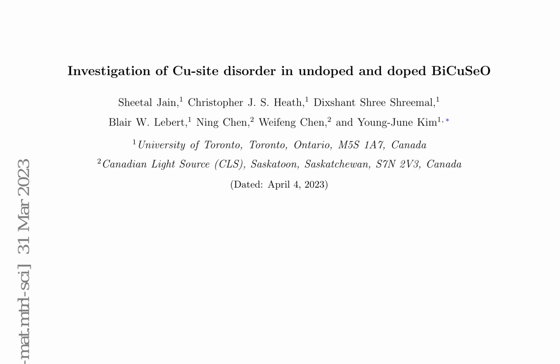To obtain quantitative information, the EXAFS data is fit to the first three shells expected for Ag replacing Cu in BiCuSeO. The three-shell fit for the data at 150 K is shown in Figure 4b, where the fitting process involves fitting both the magnitude and real part of the Fourier transform. The fits match the data well in the fitting window, yielding a goodness of fit parameter, reduced chi-squared, close to 1 for all temperatures. The fits yield the atom pair mean square displacements, sigma squared_j, for the three fitted shells, tabulated in Table 2.